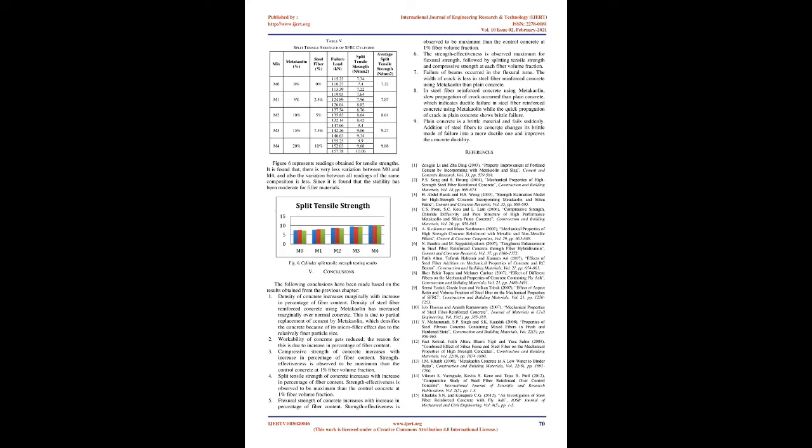Beam flexural strength of steel fiber concrete. It is observed that 28 days flexural strength increased continuously up to 10% of fiber and 20% of metakaolin, as compared to normal concrete. Hence, fibers are best suitable for improving flexural strength of structural concrete. The increase in flexural load and deflections is observed with increase in fiber and metakaolin contents. This indicates the increase in ductility of concrete. It is seen that failure of beams occurred in the maximum bending moment, flexural zone, i.e., the middle third zone of the beam. Figure 5 shows the variation in the readings obtained by shear strength testing.